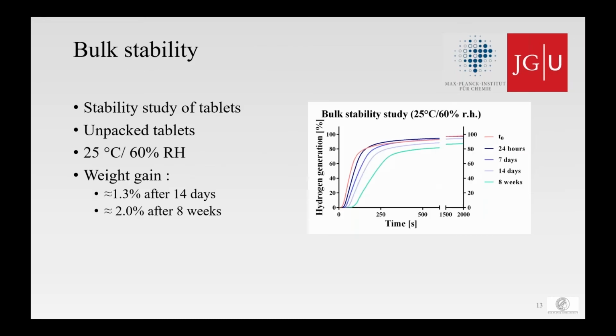So based on these DVS results, we also conducted a bulk stability study of unpacked tablets. We did this in a constant climate chamber. And from what we learned from the DVS results, we expected the tablets to be stable at 25 degrees and 60% relative humidity, which was relatively true over a moderate period of time. So after 14 days, we observed about 1.3% of weight gain, and after 8 weeks, we had 2% of weight gain. And we also took a look at the hydrogen generation speed and the hydrogen generation amount of the tablets.